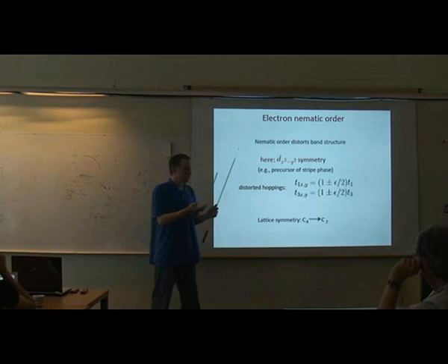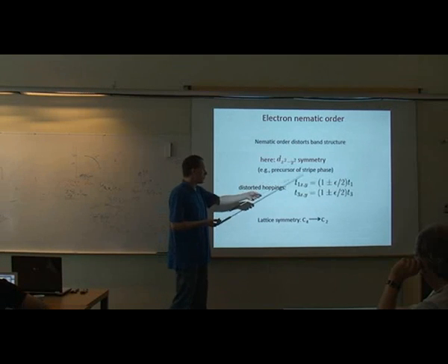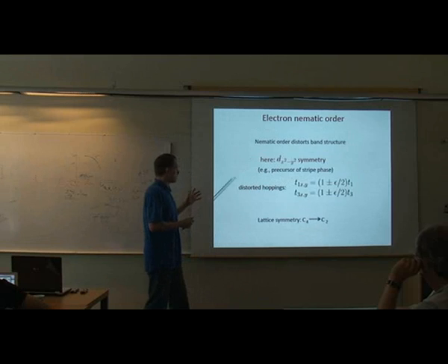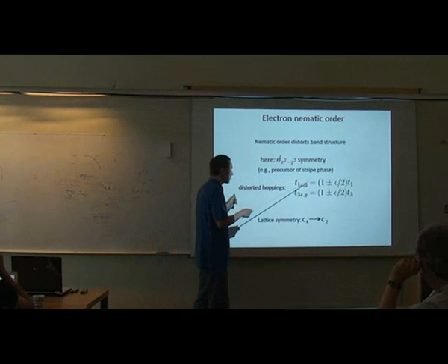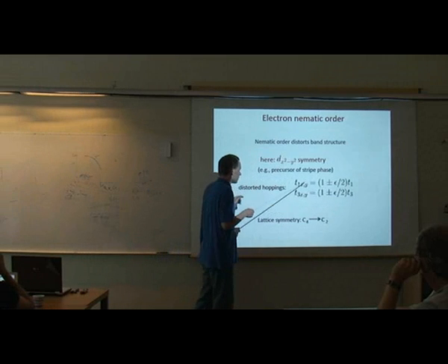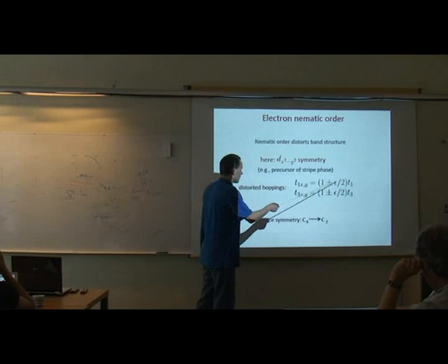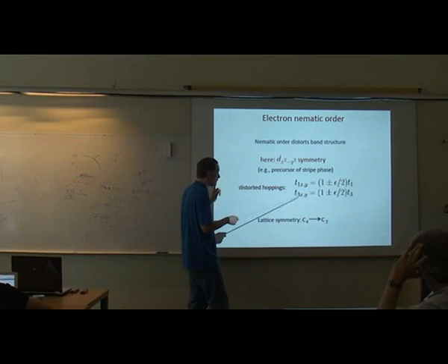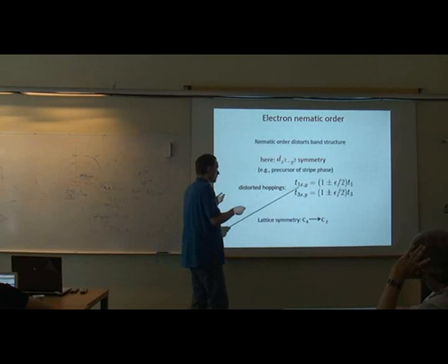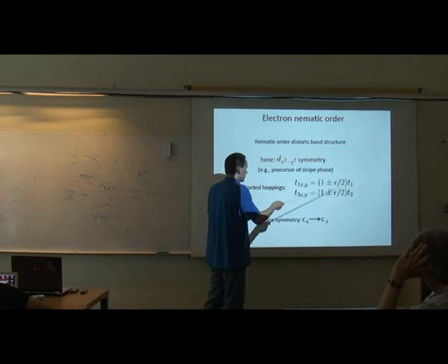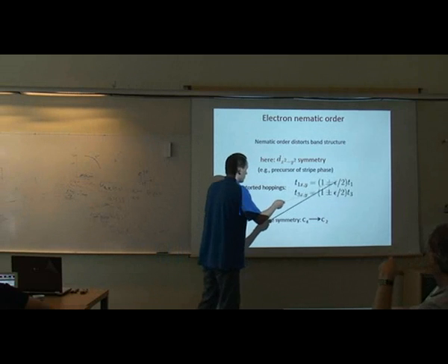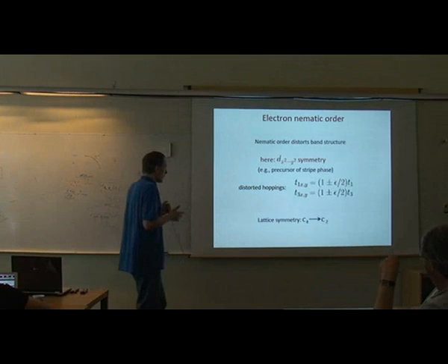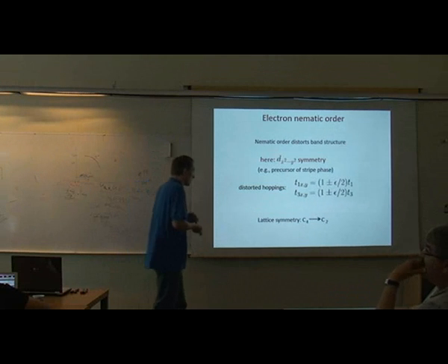This is believed to be a precursor of the broken symmetry of the stripe phase. That's simply produced like that: you simply distort the xy hoppings with opposite sign, coupling to some scalar order parameter. The nearest neighbor hopping is 1, the next nearest neighbor hopping 3. And this simply describes the linear coupling to the order parameter, which is essentially the anisotropy ratio of this nematic order.